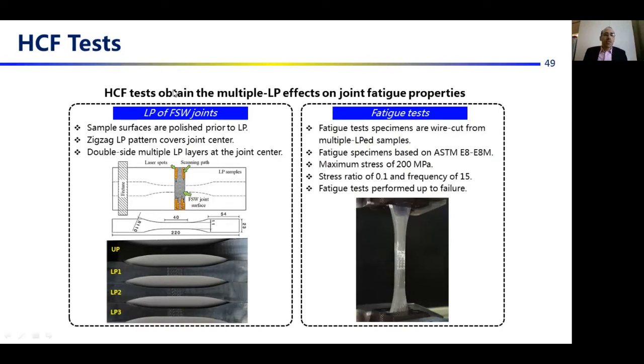For the high cycle fatigue test, we obtain the multiple laser peening effects on joint fatigue properties, and laser peening is applied with the same pattern to cover all over the joint area, and fatigue specimens are cut from the laser peened samples. Fatigue tests are conducted with the stress control regime with the maximum stress of 200 megapascal and the stress ratio of 0.1 up to the sample failure.